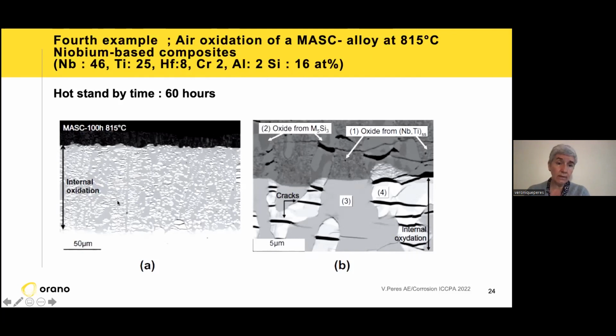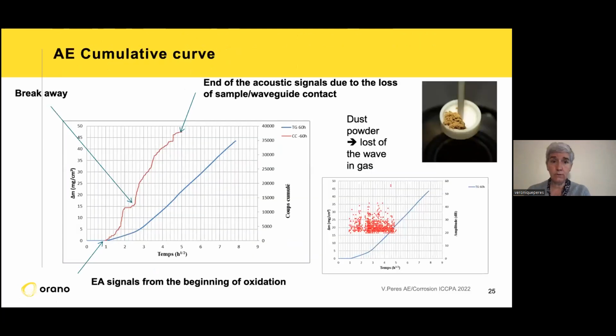And you can see here some different behavior. You have the internal oxidation of one part of the phases, and the second one is not oxidized, but you have some cracks coming from these different phases. So it is also possible to follow the oxidation by acoustic emission, which we did. In blue, sorry, in blue you have